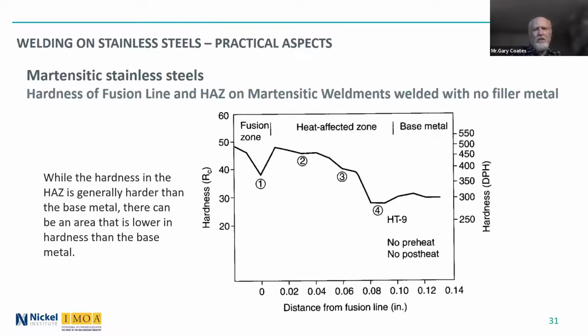I show this graph. It's actually a martensitic stainless steel welded without filler metal. So you can see on the left-hand side where the fusion zone is, the distance from the fusion line. So the weld metal is a little bit harder. Then there's a bit of a weaker area right at the fusion line. Then you go back to the higher hardness, and then it starts dropping as you get to the base material.